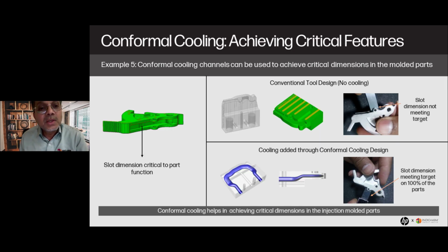And the same thing here, if you look at this component, because of the uneven cooling, in the conventional tool design you only see straight lines. That was not sufficient for uniform cooling on the slot area here. With the 3D printed tool design, you were able to get a conformal cooling channel much closer to the area where the cooling is required. So we were able to significantly reduce the distortion in the slot. Considering that we were doing 100% inspection, sorting out and losing 10-20% of the components, we were able to get 100% yield, and we eliminated even inspection as well, because we were so confident about the process with the new design.